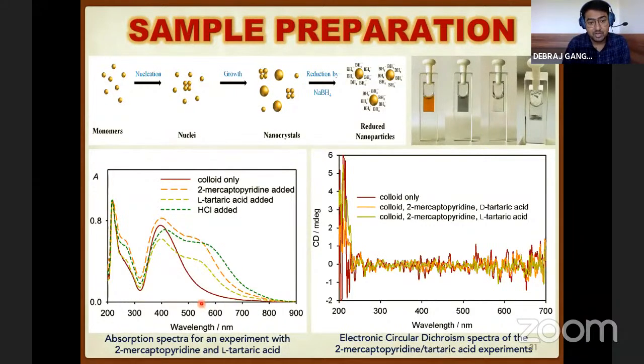And as we have used a 532 nanometer laser, you see that it's absorbing in this 532 nanometer range. So there is a possibility of resonance when we observe the surface enhanced Raman spectra. And this resonance may give us very strong bands in SERS as well as in surface enhanced Raman optical activity as well. And here I have shown you the electronic circular dichroism spectra. You see there is nothing.